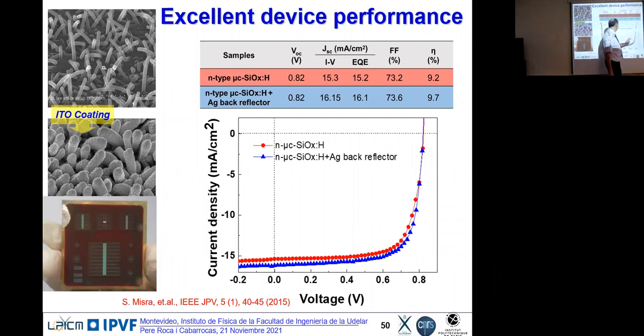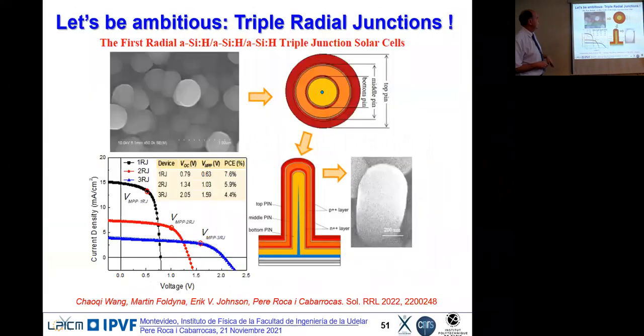The device works. At the beginning, the cells were like this. So the first PhD student had something working, I would say perfectly, with a good fill factor, efficiency, current, VOC, and this is the size of the device that we are making with 100 million wires per square centimeter. And then once you have done a single junction, you can make a tandem. So you can have a PIN and then a second PIN and then a third PIN. And with that, you have a triple junction.